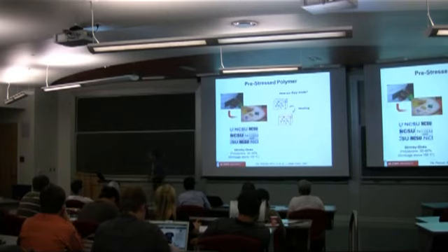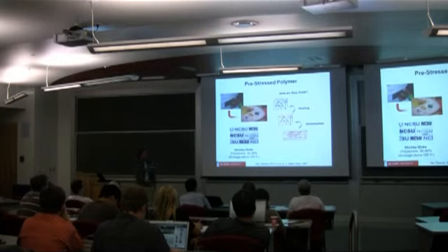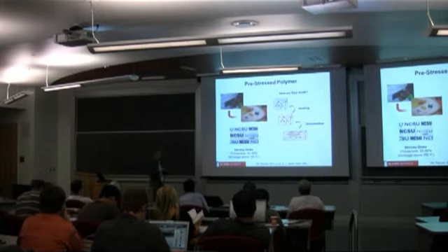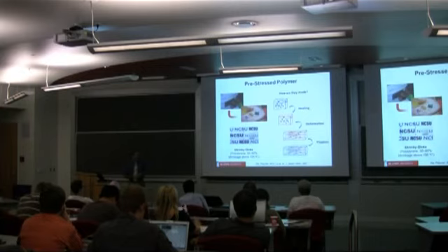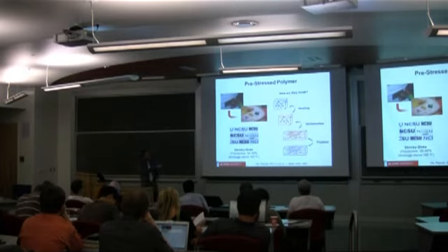And at that point, you take this thing and you stretch it. And fortunately for us, this is all done commercially. But you stretch it, and the polymer chains are now stretched out. So they're in a state they don't want to be in. They want to be coiled up. That's their energetically favorable state. And so if you cool this down, you basically trap it so that it can't flow. And when you heat it back up, it reverses. It gets hot, it relaxes, and goes back to its original state.